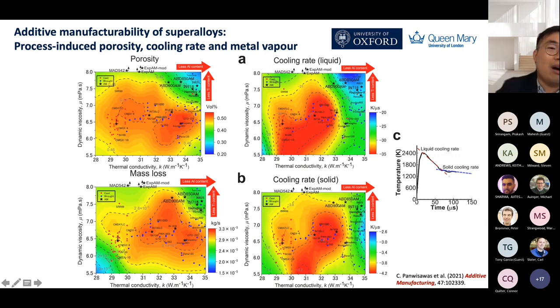So we benchmarked on that, and then we generated what is called a thermal fluid map to say something about manufacturability using porosity and cooling rate in the liquid state. As is shown here, from liquid to solid there are different cooling rates, as you may notice in your measurement if you do some in-situ thermal imaging and monitoring. And more importantly, from the high fidelity model, we can generate something called a mass loss map as well for superalloys.